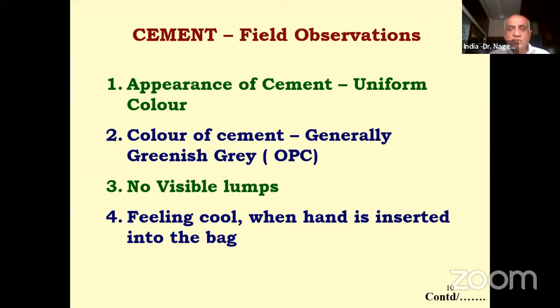This is not always true, because cement manufactured in the plant normally gets used very early. So that means very fast usage will be there. In that case, cement will not always be cool. It will instead be hot. So if a hot cement is brought to the site, is there any concern? If it is hot, only the water demand slightly increases. Other than that, there is no issue. If the clinker is cooled and then ground, we can say that it can be slightly cool. But because of the grinding also, the temperature may increase. So if the cement is hot, nothing to worry. The water demand might slightly increase. So these are some of the field observations.